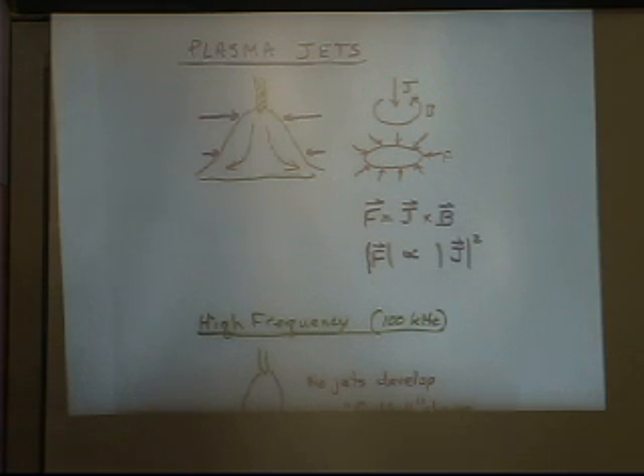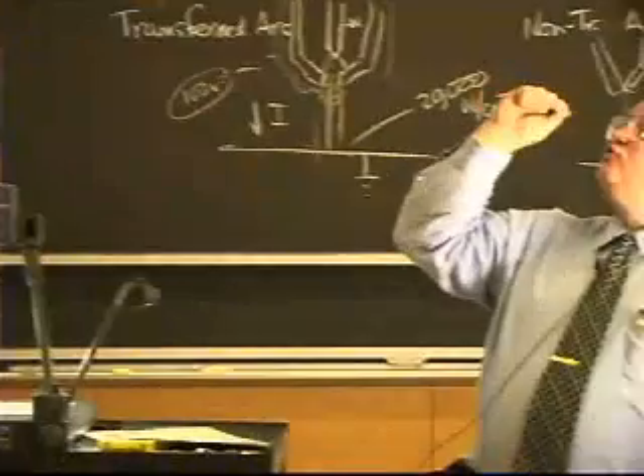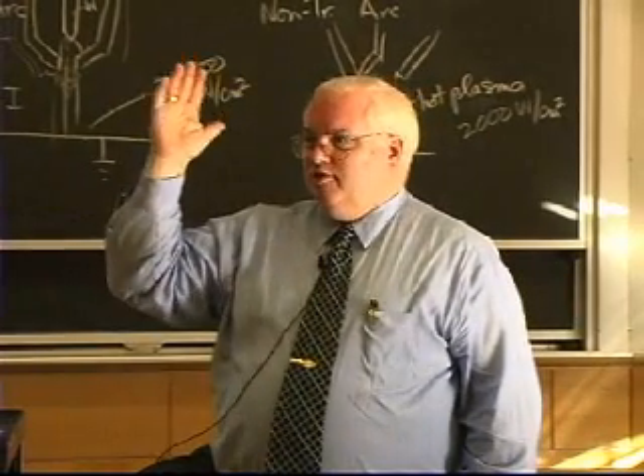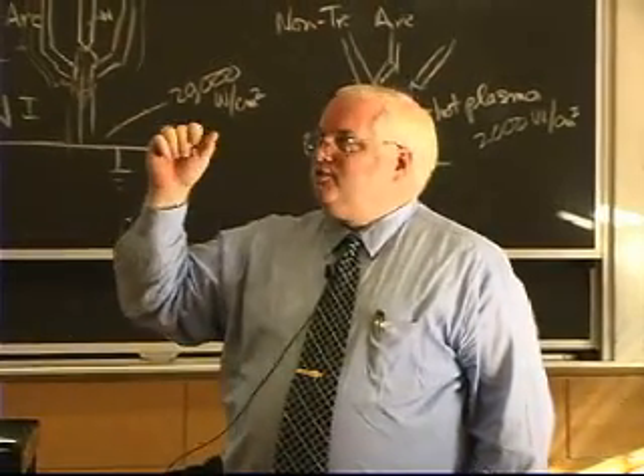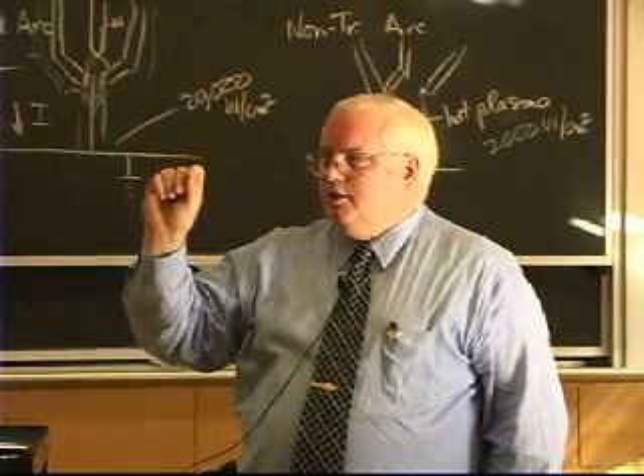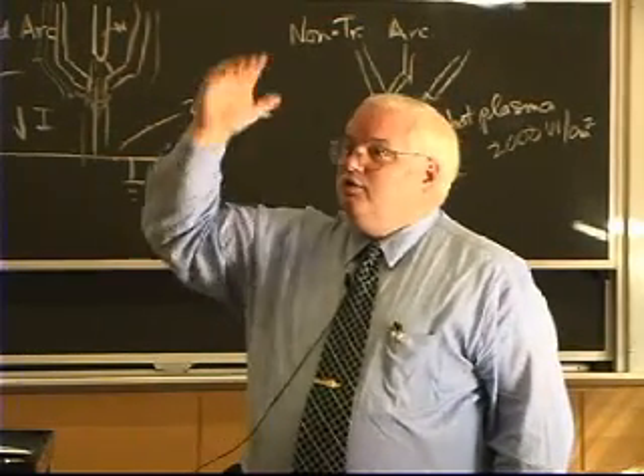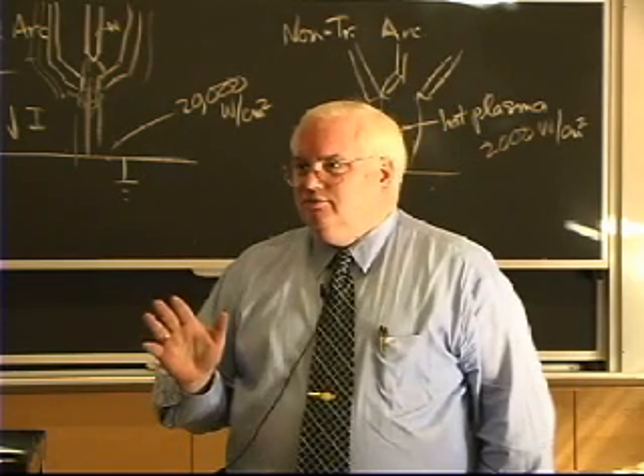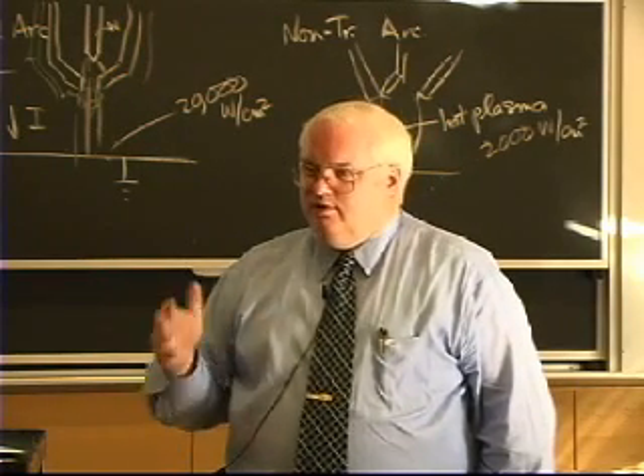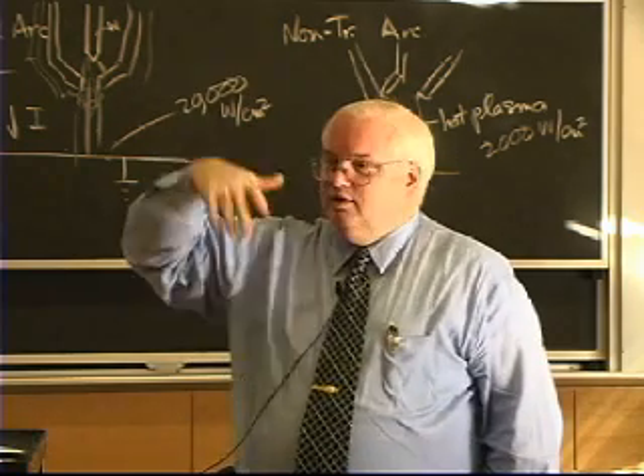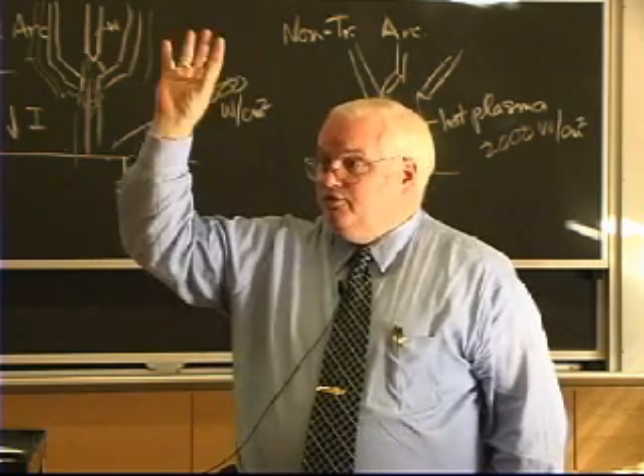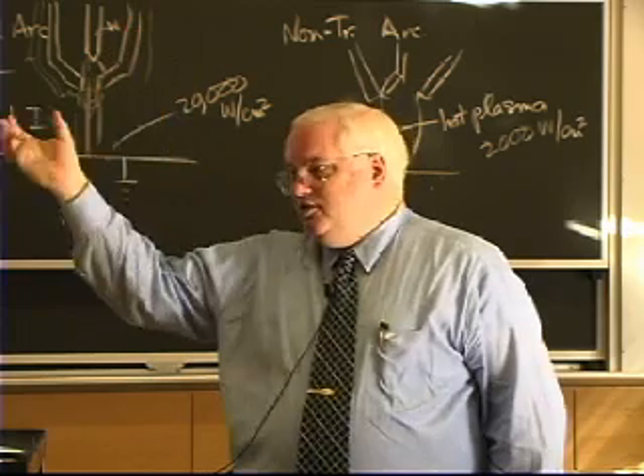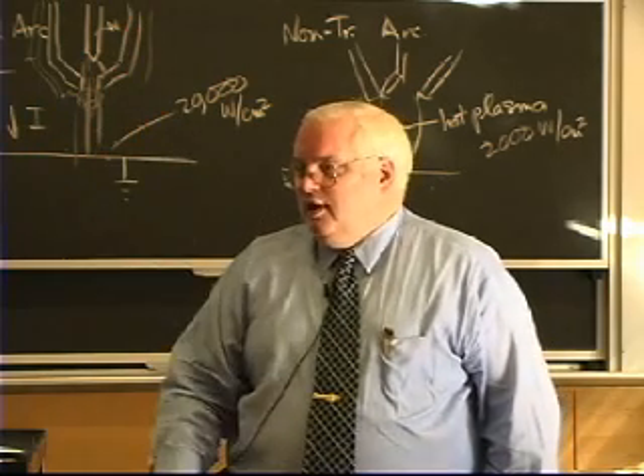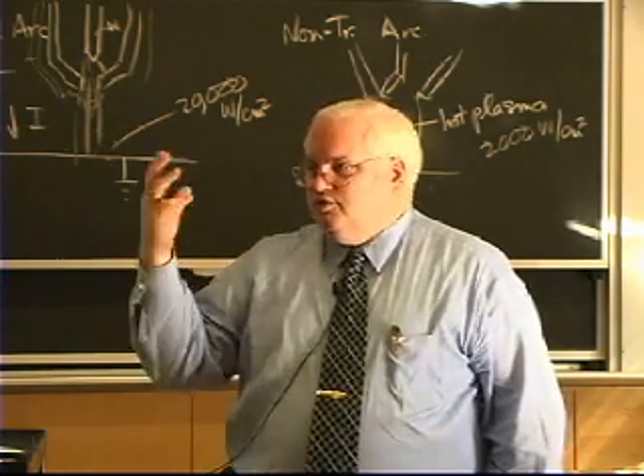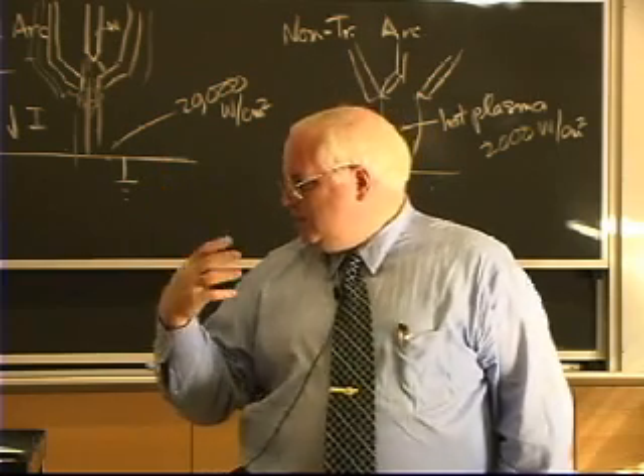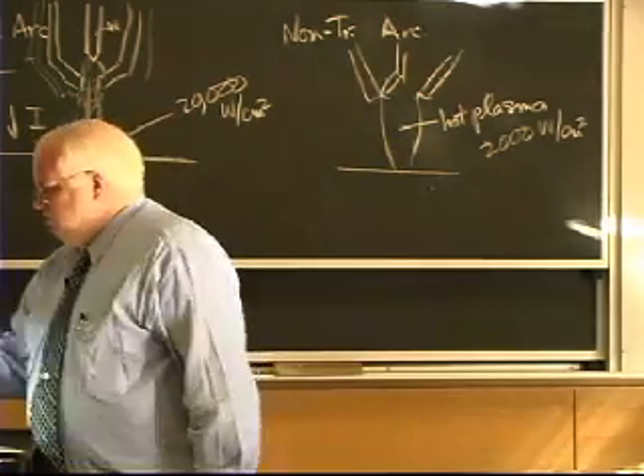And in fact, that's why I can weld overhead. Why do the drops go up when I weld overhead? You never thought about it before, did you? Some people say, well, I actually touched the little drop and surface tension carries it up. No, no, no. If you actually look at it, you got drops going up against gravity if they're small drops. Turns out if they're smaller than about 1/16 of an inch, the plasma jet is sufficient to blow them up, and then surface tension does hold them in there. Remember, if the weld pool gets much bigger than a couple of 1/8 of an inch, it's going to fall back down your face because surface tension won't hold it in. Gravity becomes dominant. But the reason I can weld overhead is because of these plasma jets.